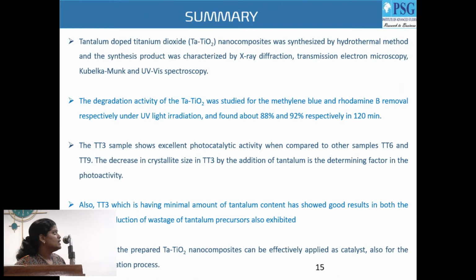Tantalum-doped TiO2 has been synthesized by hydrothermal method and characterized by X-ray diffraction and transmission electron microscopy, and optical studies by Kubelka-Munk and UV visible spectroscopy. Then the degradation with this tantalum TiO2 has been done for both dyes at 365 nanometer UV light in 2 hours. Then tantalum at 3% is showing excellent characteristics when compared to 6 and 9.